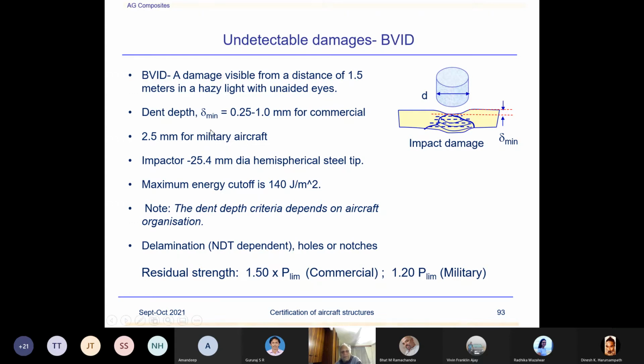And say for military aircraft, suppose you're dealing with a military aircraft, the BVID requirement for a military aircraft is 2.5 millimeter. Now 2.5 millimeter is a severe requirement. It's quite, in fact, detrimental compared to the commercial aircraft. Impactor, when you are trying to consider this damage, there's a limit prescribed: 25.4 millimeter, 1-inch steel impactor tip. Maximum energy impact. Now what happens when you're trying to impact, suppose a 1 millimeter plate, it would require less energy to create the same dent. If it's 5 millimeter thick, it would require high energy to create the same dent.